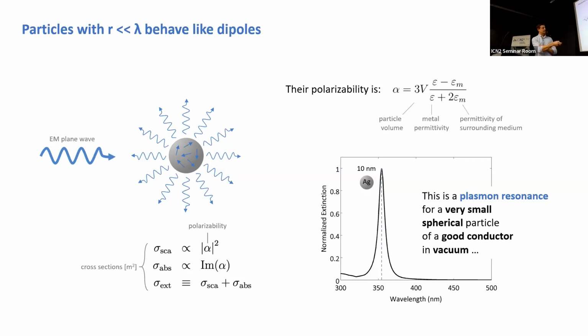If you remember, it's a very small particle, because we were in the dipole approximation where the radius is much smaller than the wavelength. Spherical particle, because this actually works if your particle is very tiny, so it's spherically symmetric. Of a good conductor, because we said the imaginary component of silver, we can neglect it, and in vacuum. But all these things actually affect the position of this resonance and the shape of this resonance. So in fact, the plasmon resonance will depend on the size, on the shape, on the composition, and on the environment of our nanoparticles, right?